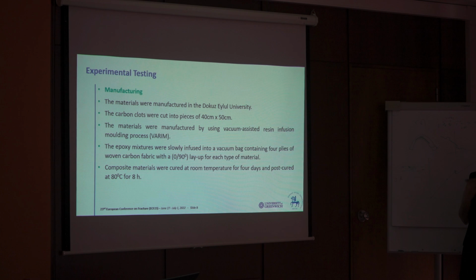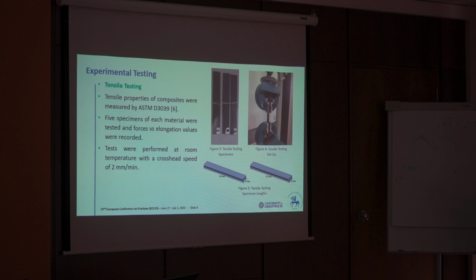And then after that, all the materials were cured at room temperature at first, but then they were cured at 80 degrees Celsius for 8 hours, including all the ones with or without nanomaterials. For the experimental testing, we ran the tensile testing and the 3-point bending testing in order to estimate the tensile strength and the flexural strength of the materials. At least 5 specimens of each material were tested, and all the experiments were run according to the ASTM standards, and all the span lengths and the tensile testing and 3-point bending specimen dimensions were chosen according to the ASTM standards.